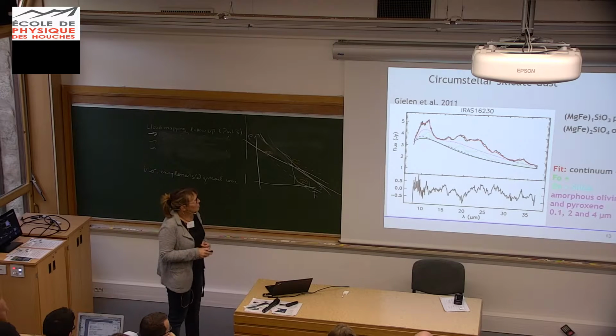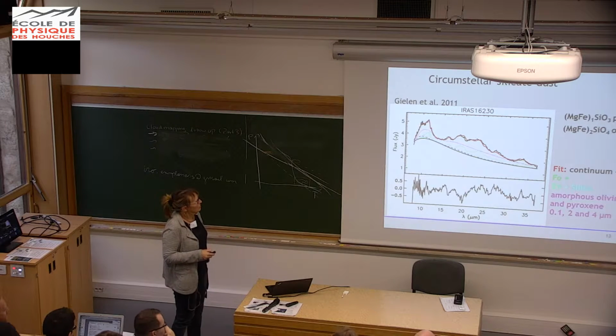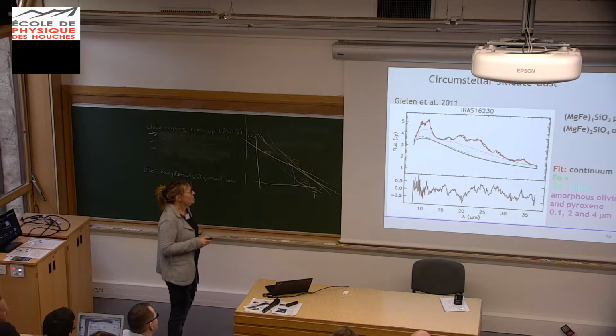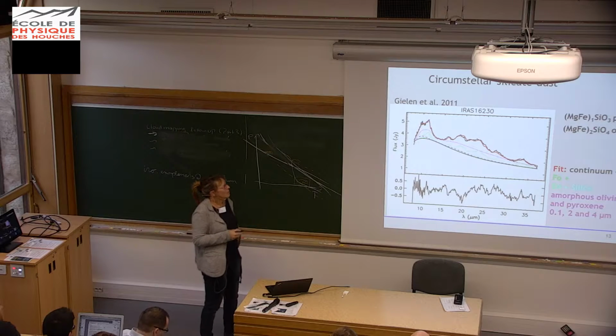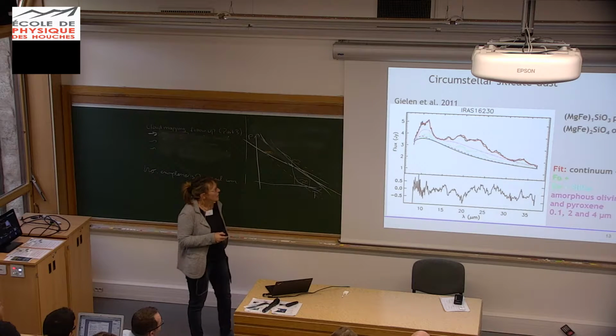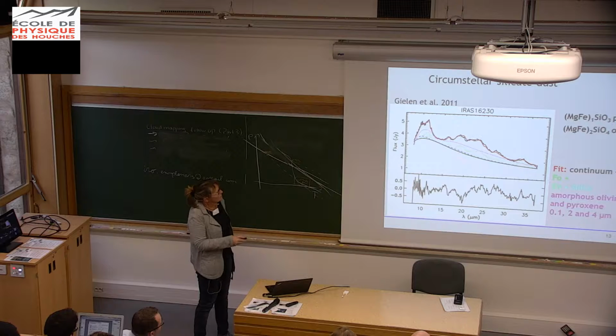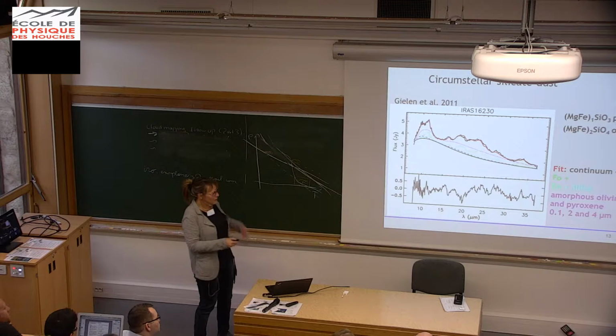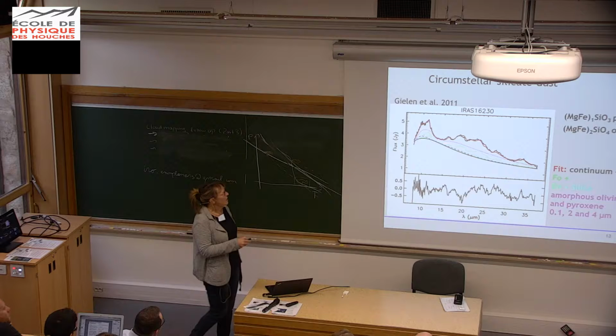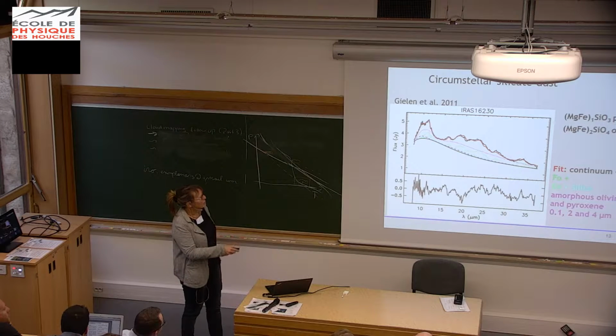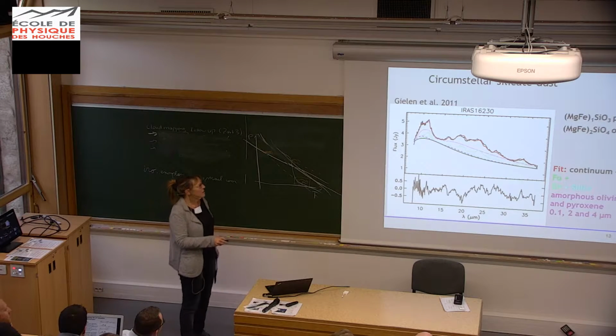So this is a kind of outcome from our condensation and spectral measurements. This is a nice fit of emission from an oxygen-rich binary star presented by Gielen et al. 2011. You can see, after subtraction of a continuum, the emission bands which have a certain structure, and you can fit these bands with an amorphous part - amorphous olivine and pyroxene, iron containing, with different sizes. To get the structure here, you have to add some forsterite and enstatite silicate.